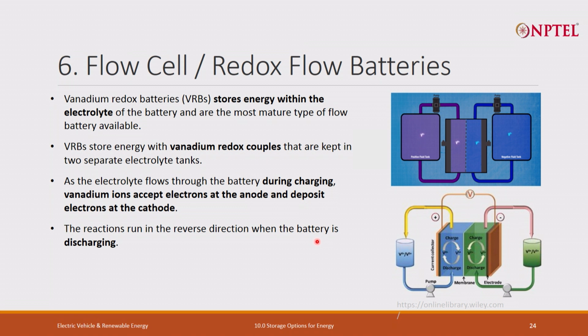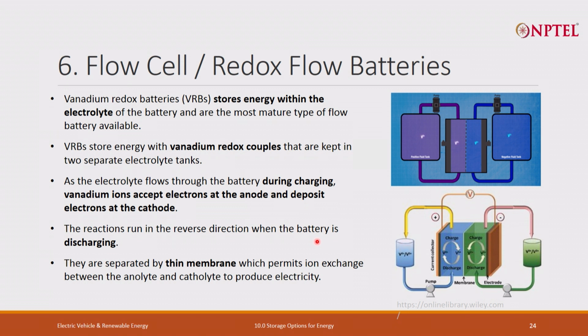So, after a certain time when the battery gets discharged, you again charge it, discharge it. Similar principle to lithium ion storage, but the life cycle of this vanadium storage is much more than the lithium ion storage. Both the electrolytes are basically separated by a thin membrane which permits only ion exchange, not mass exchange.